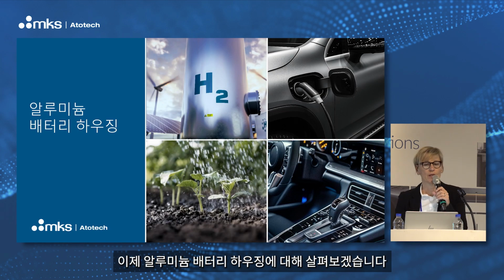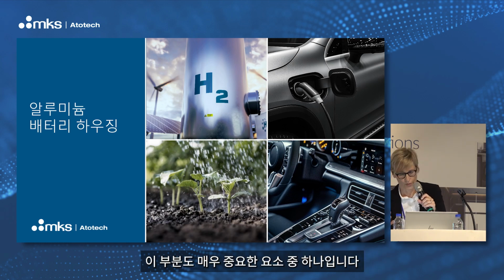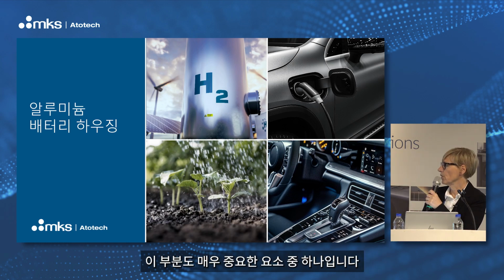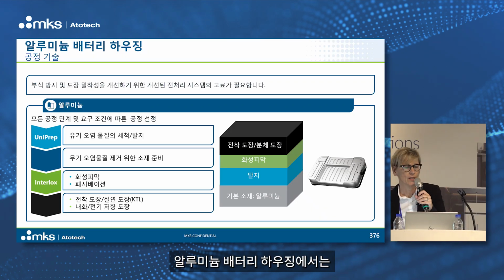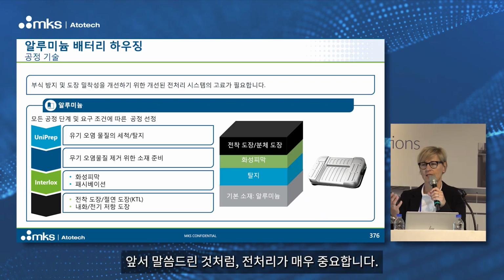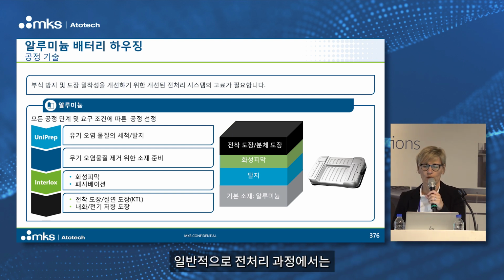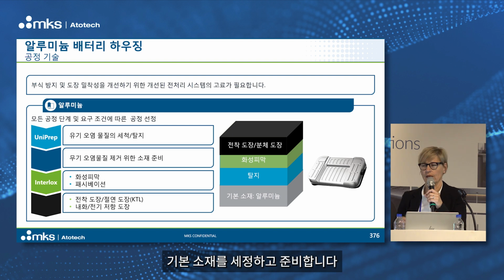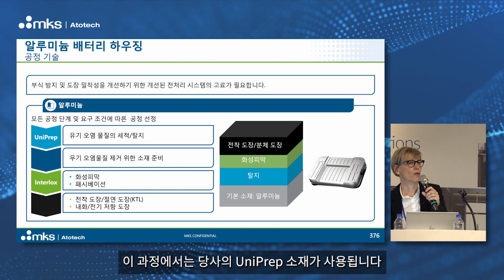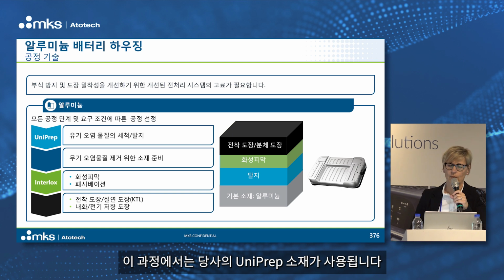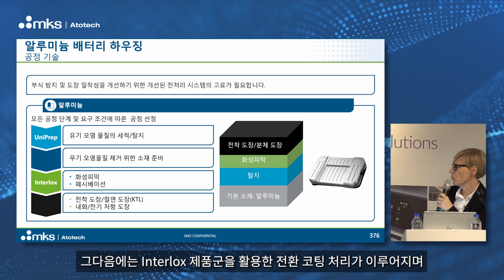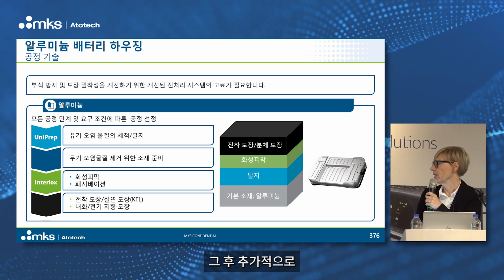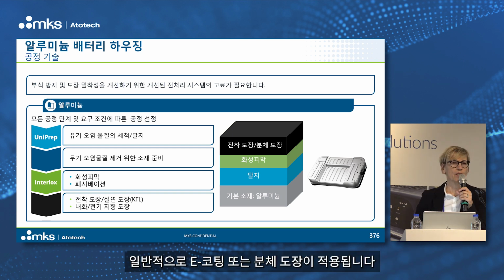Let us now have a look into the aluminium battery housings, because that's also a very important piece of that cake. In aluminium battery housings, we also have a lot of technologies, and as I said before, the pre-treatment is really very important when you are looking into the waste. Normally you clean the base material with one of our UniPrep materials and prepare it for the conversion coating, which is then a part of the Interlox family. And then additionally afterwards there is normally an E-coat or a powder coating on top to protect for high level corrosion performance.